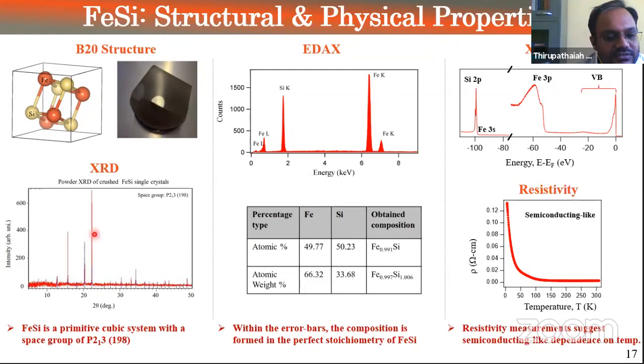This was the XRD, although it's very bad. I was lazy to collect a good XRD pattern, but this explains that the measured crystal is indeed the desired space group, which is P2_13, number 198. The EDX measurements say that within the error bars the crystal composition is perfect, in the stoichiometric ratio, iron silicon, without any impurities. And before performing any ARPES measurements, we also looked for any other impurity atoms present there. And this clearly says that there is no other impurity except iron and silicon.